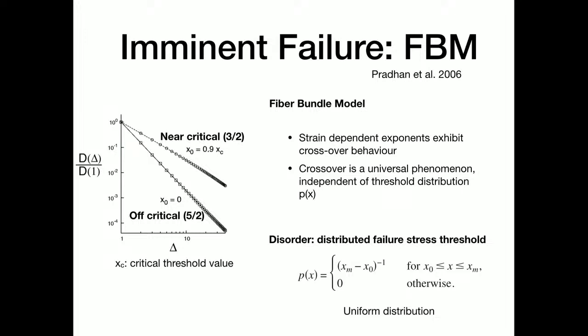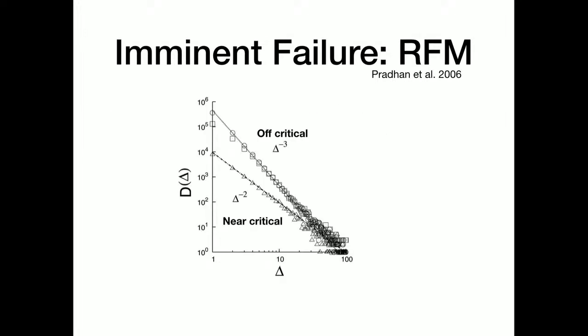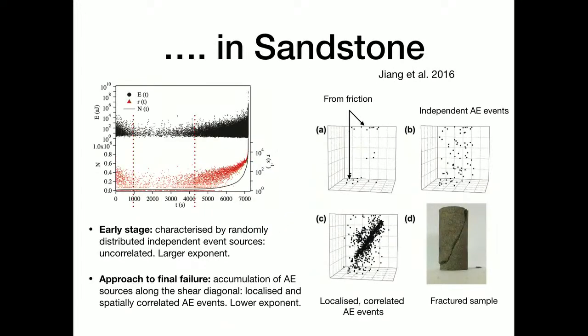And what is found is that from what was told earlier, which was 2.5, near critical there's a crossover to 1.5. This crossover in the same study is also shown to be a universal phenomenon independent of threshold distribution. For variable distribution also it was shown. And then in the same study there was also that in the random fuse network, you see exactly the same type of crossover behavior from an exponent of 3 to 2. So there is an indication of imminent failure, which is a very interesting idea.